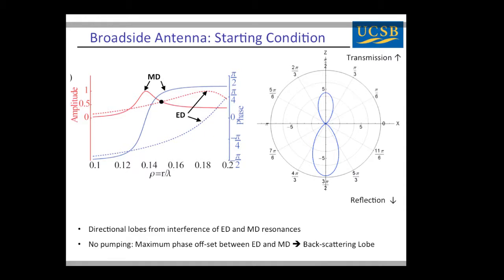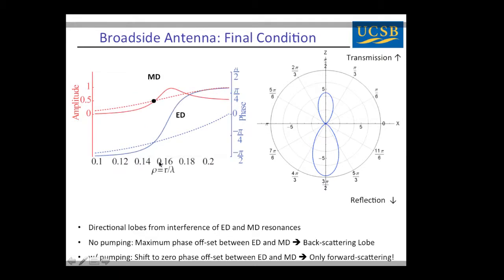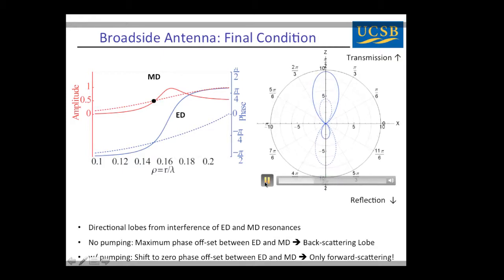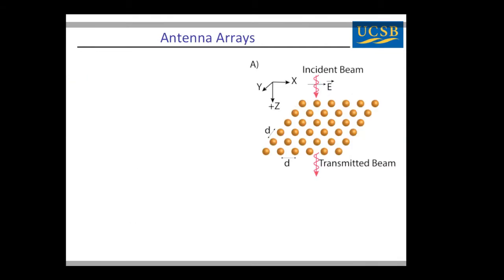Okay? So now as we introduce free carriers, all of these curves are going to shift to the right. And so if you keep your eye focused on the dot, it's sitting here at about 0.15. And so now if we introduce free carriers for that same wavelength, our amplitude and our phases are equal. Okay? So what happens is we pass from one side of resonance to the other. I'll show you now again in this animation. And what you'll see is our reflection lobe primarily becomes a transmission lobe. Okay? So by controlling within a single particle the relationship between these two different modes, we can also create directional radiation patterns. Okay? So how might we use this in a phased array?